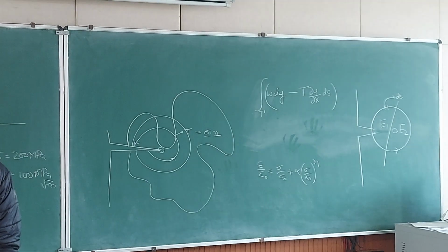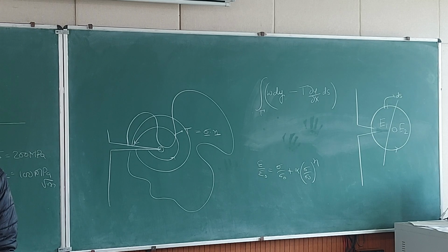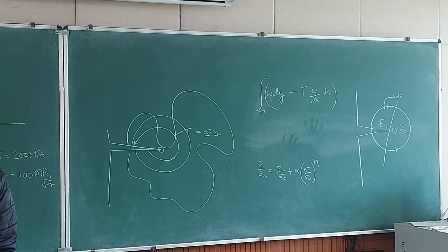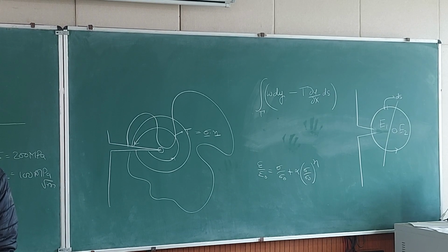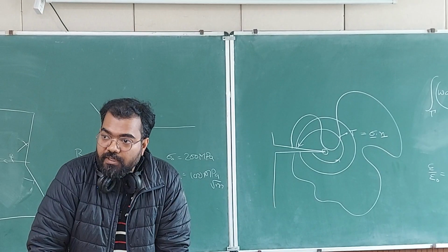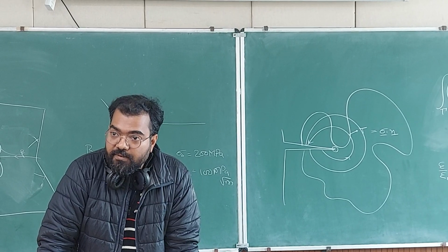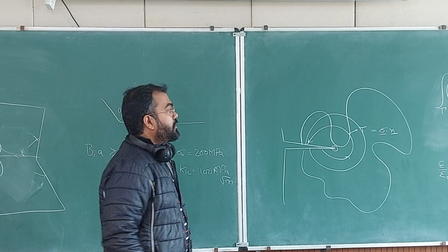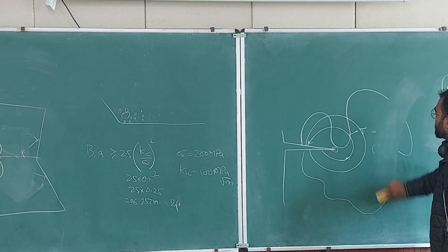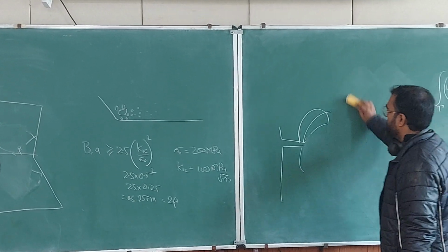Okay, and there is a material which is deforming in a different way, which we don't know about, and that is happening at the crack tip. So with the crack tip there is a process zone. Both of them are acting as a source of energy or sink of energy, sink of energy if the value is negative. Okay. So Rice does this and says that by using this line integral and assuming the material to be non-linear elastic, we can